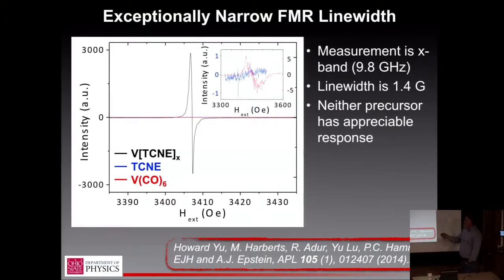So this is the ferromagnetic resonance spectra of V[TCNE] grown via this optimized synthesis process, and you can see it's incredibly sharp. The line width of this scan is 1.4 Gauss. That 1 Gauss line width we can get fairly reproducibly. And the red and blue lines, which you can't really even see on this scale, are just the precursors, because the first thing we thought when we saw this was, wow, that's a really nice ESR spectrum. I wonder what's contaminating our sample.